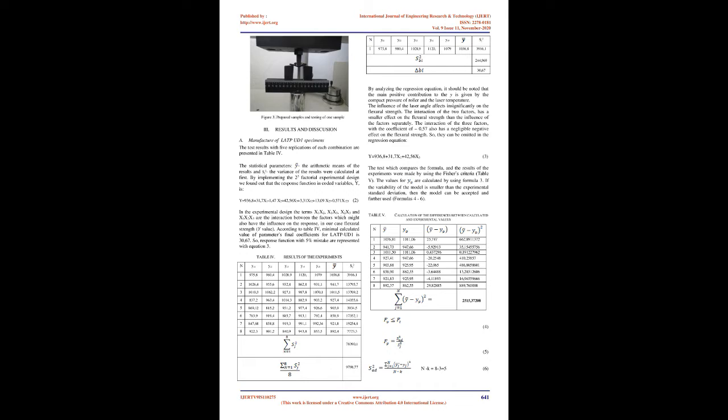For the statistical analysis, 5 tests of each combination were realized, so the number of replications is 5. With that assumption, we have taken the first-order linear model with interactions to predict the response function, i.e. the flexural strength of the laminate specimens within the stated study domain. An investigation of the effect of technological parameters on mechanical properties of laminate panels was performed.